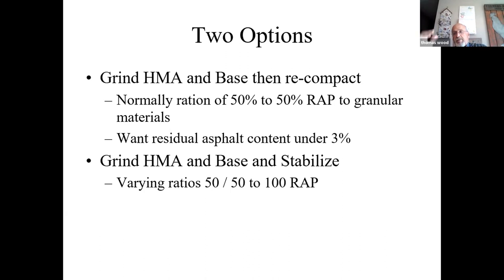So we go back to that same county road where we got 6 inches of bit over 5 inches of gravel, and I want to stabilize it, but I'm only going to stabilize 6 inches of road. All I need to stabilize at is a G 1.5. So what I would do there is I would grind 6 inches of all the HMA into 1 inch of the gravel just to keep the teeth cool. And then I would stabilize the top 6 inches.